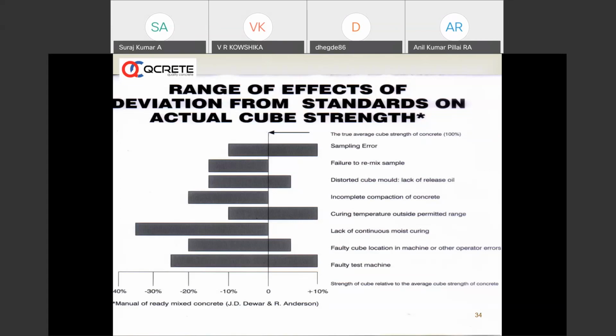You are going to have lower strengths, especially in high temperature areas, let us say Chennai, Hyderabad, even sometimes in the hot summer situations in Bangalore. If lack of curing happens, evaporation rates will be higher. There will not be sufficient water inside the body of concrete, and then there will be a lot of unhydrated cement particles in the body of concrete because of lack of moisture available, and hence it will lead to significant losses of strength.